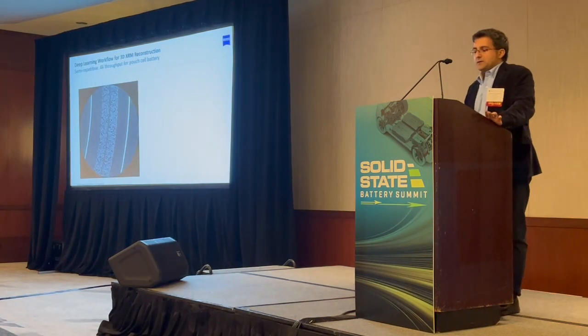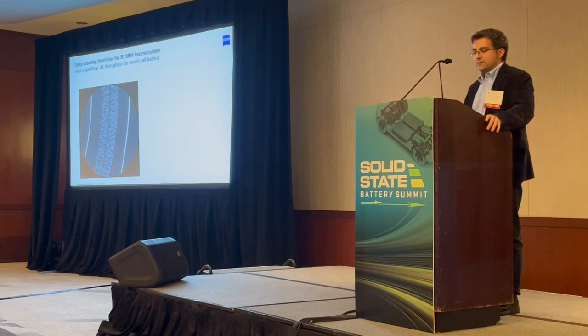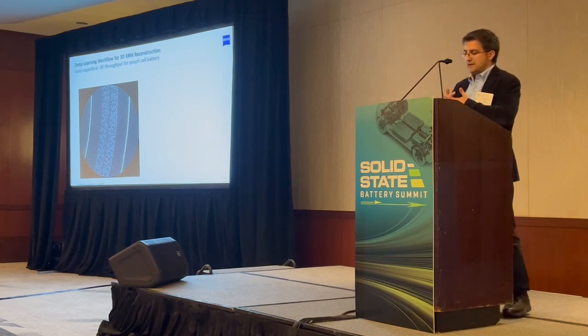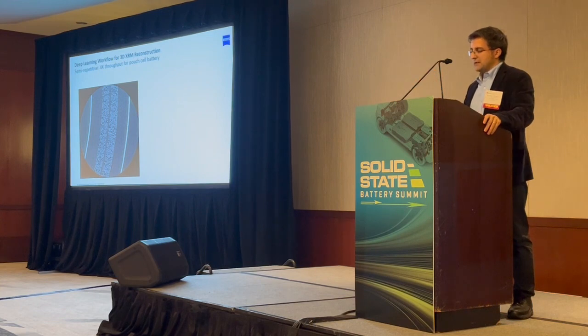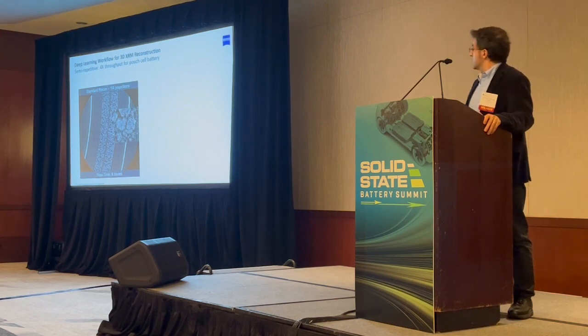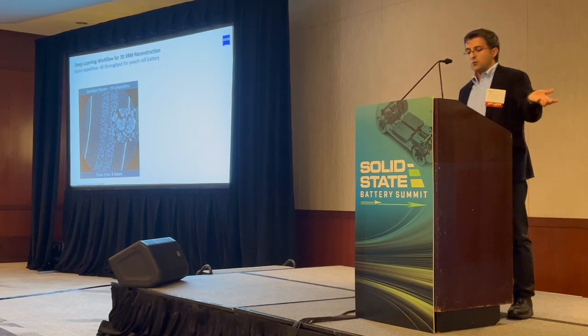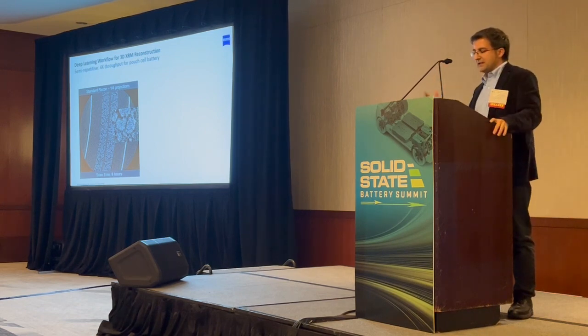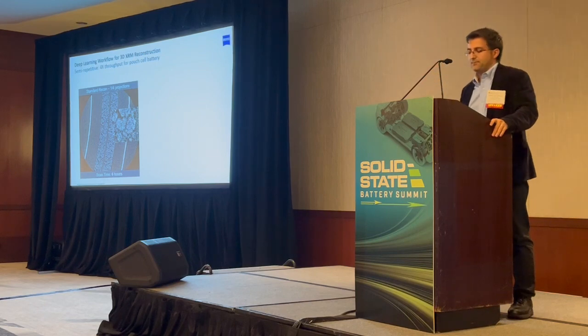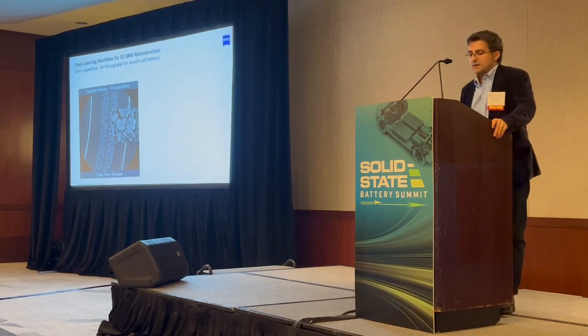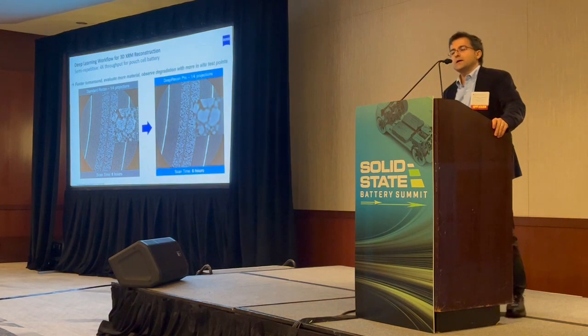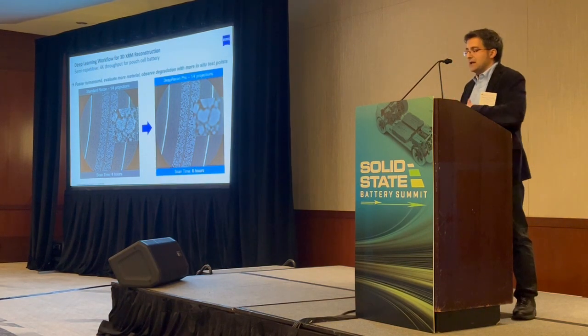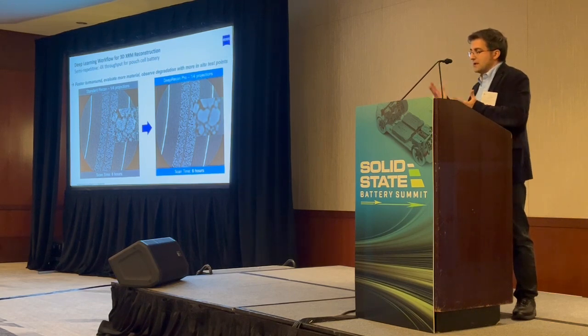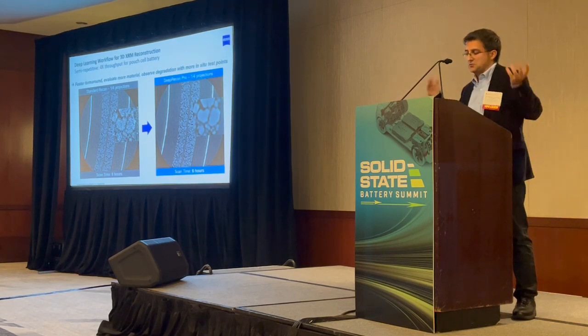Let's look at another example of a semi-repetitive application, such as taking a look at the microstructure of the lithium-ion battery in a commercial pouch battery in this case. As you can see, if we want to image faster, then we could reduce the projections to 1/4 with the standard reconstruction, but then we start seeing noise in the data. If we do this with DeepRecon, then we can see that we get rid of the noise and we recover the data. And that's the whole point of this network, or DeepRecon reconstruction.